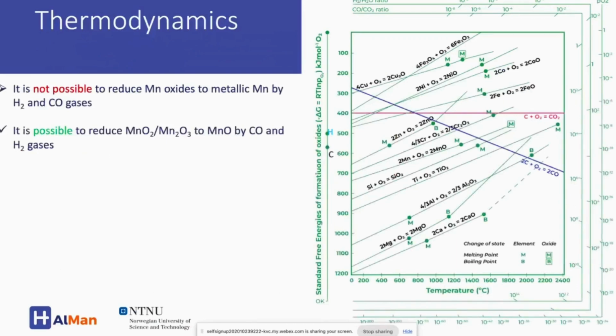Here you see the thermodynamics behind the process. I don't go to the details, but in short, I mentioned that it is not possible to reduce manganese oxides to metallic manganese by using hydrogen and CO gases. So we have a limitation regarding the materials and the thermodynamics. But it's possible to reduce manganese oxide down to MnO by CO and H2 gases.